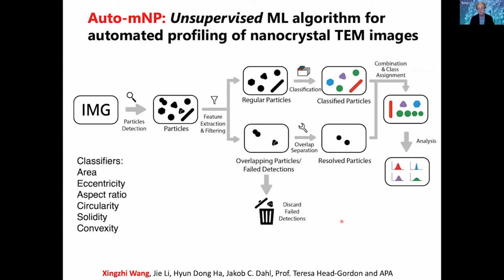So what we have now is an algorithm which will take very large numbers of images from the transmission electron microscope of a nanoparticle sample, and it will detect the edges by the contrast change as it encounters the particle, and then we will classify the particles according to a number of classifiers. The area, the eccentricity, the aspect ratio. A sphere would be 1 to 1. A rod would have a large aspect ratio.